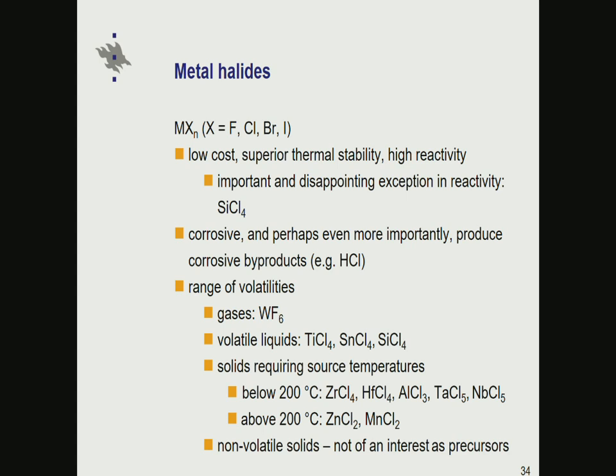So I will start now going through these homoleptic metal precursors. I will start from metal halides. Metal halides, in my opinion, are severely overlooked precursors in ALD. People are scared of metal halides because they produce corrosive byproducts, and they may be corrosive by themselves. But the fact is that, first of all, these are very low-cost precursors. Most of the other precursors are actually synthesized from metal halides. That's why these are cheaper than the others.